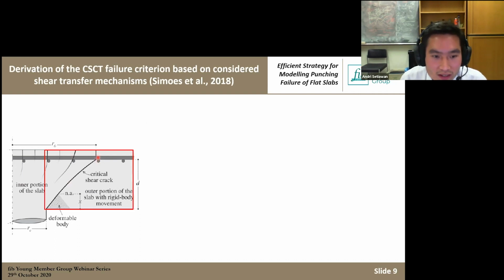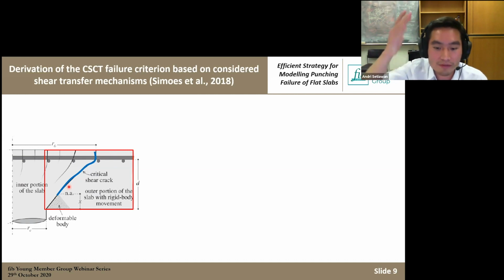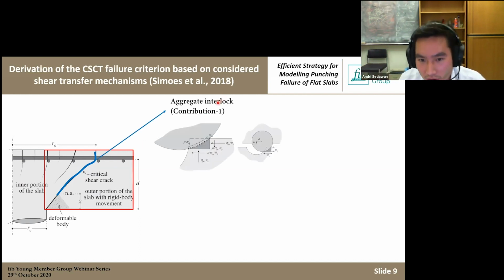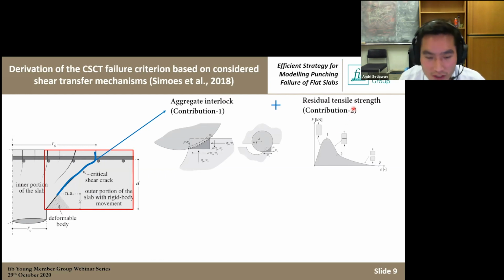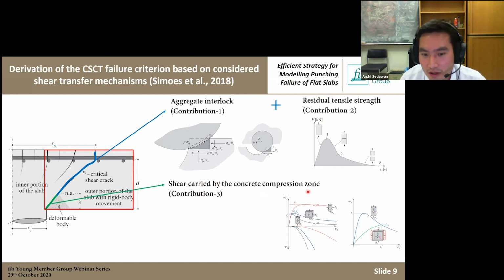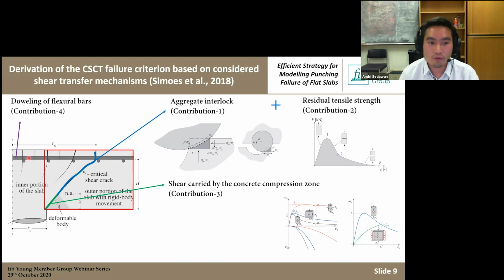So we see in here the critical region where we have punching. This blue region is the discrete crack, which is basically the crack that occurs above the neutral axis. And in here, we have the contribution of aggregate interlock from this part, and also the contribution of residual tensile strength. I call it contribution 1 and contribution 2. And then in the compression zone, we have shear carried by the concrete compression zone. I call it contribution 3. And the last thing, we also have the contribution from the dowelling of the flexural bars.